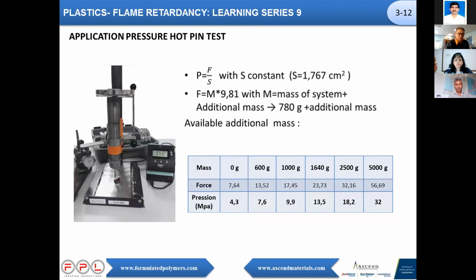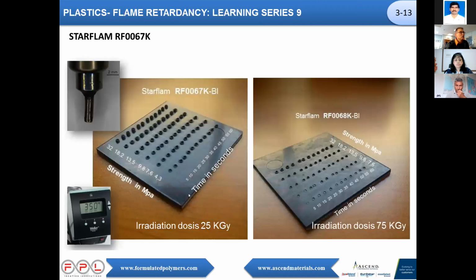So the real question of the customer is, yes, it withstands high heat short term, but what is high heat short term? What heat? What duration of time? So we made our own approaches in which we can change the weight and we can change the time. So we basically draw some curves. On this picture, you can see for example this product irradiated only 25 kilogray, which is not a lot for our product. And you see here time ranging from 5 seconds to 1 minute and weight from 4 megapascal to 32 megapascal.